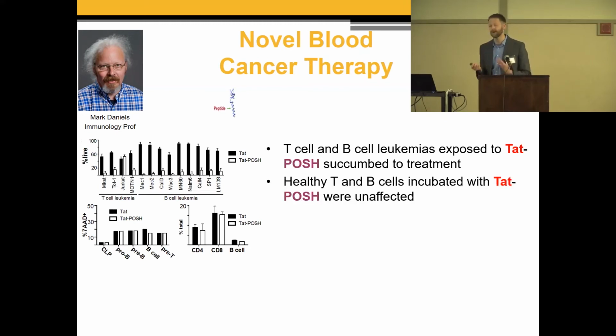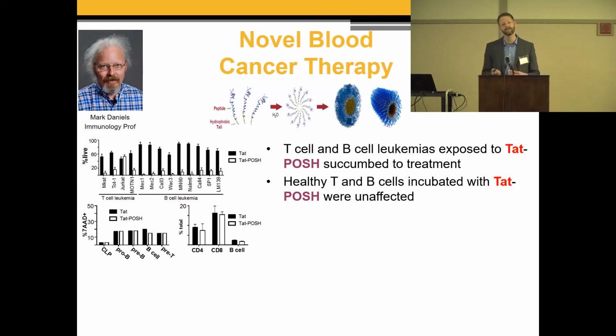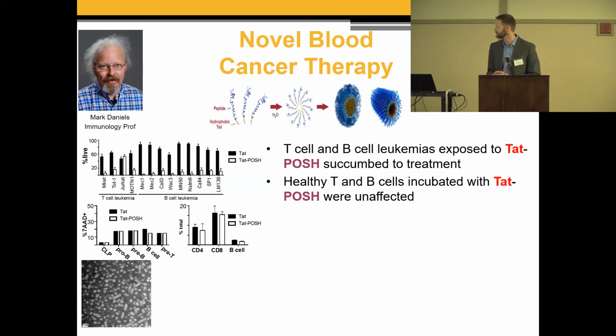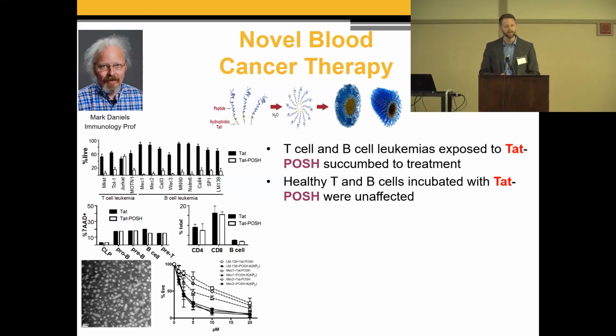So that's great, but the problem is a peptide drug by itself can be pretty limiting on its ability to kill cells. So he was very interested in having some sort of drug delivery solution. So what we do is we make lipidated peptides. By adding this lipid region, we actually get self-assembly into different nanoparticles. And those nanoparticles for this application are about 10 to 20 nanometers in size. So good for trafficking in the blood and getting to the cells of interest. So what we see is comparatively to the standard peptide therapy, our nanoparticle therapy actually helps pretty significantly.